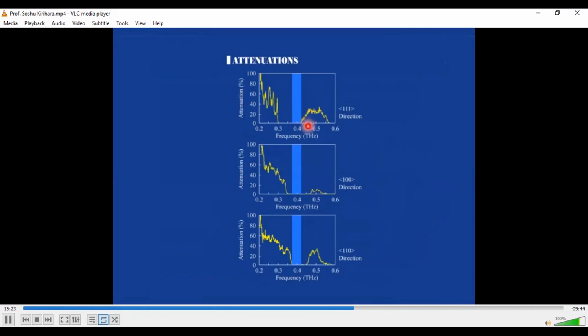This figure shows the obtained transmission attenuation spectrums. You can see the 111, 100, 110 directions, and we can obtain the photonic band gap in a similar frequency range. This blue band shows the common region of all crystal directions. For example, a 0.4 terahertz wave is impossible to transmit in any direction. This means the perfect photonic band gap formation.